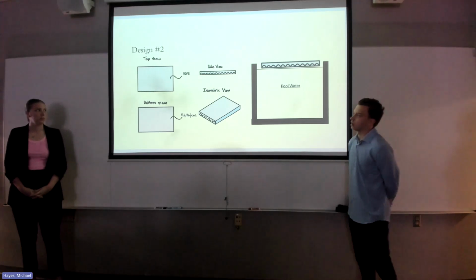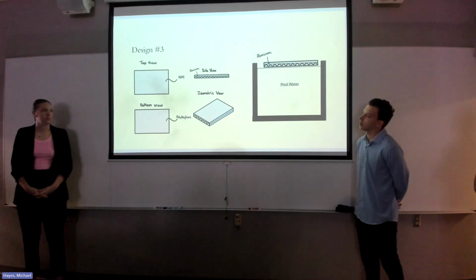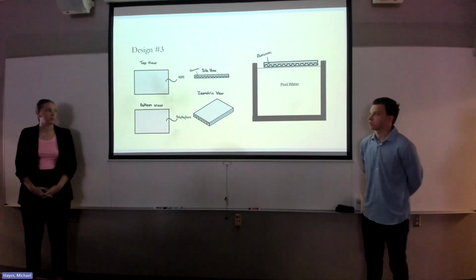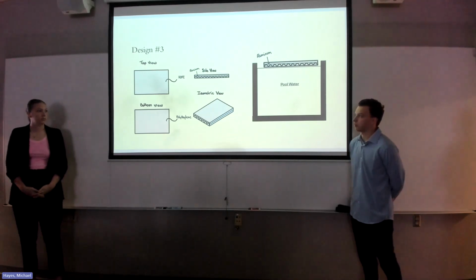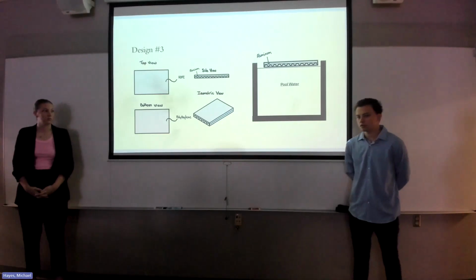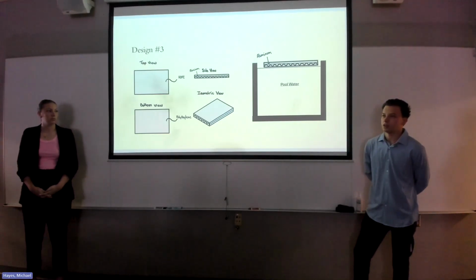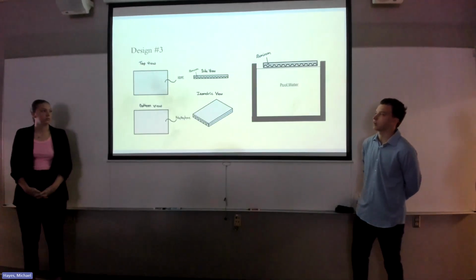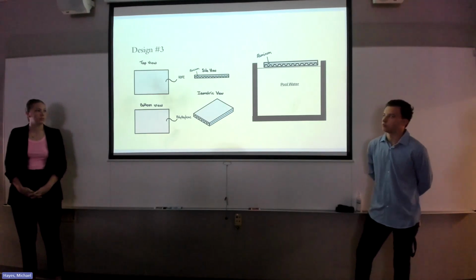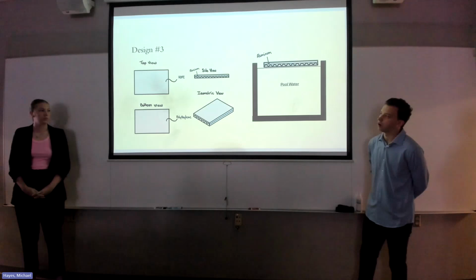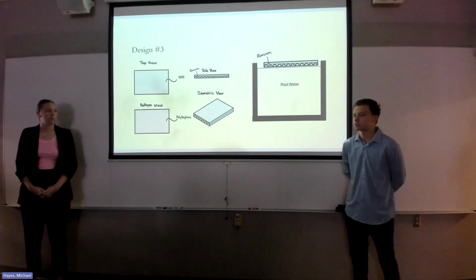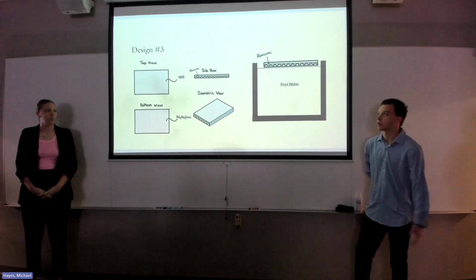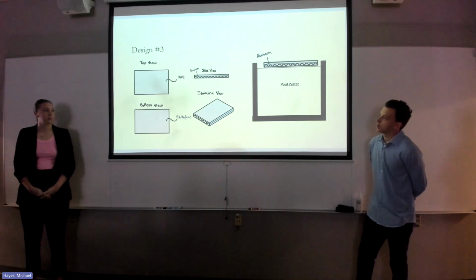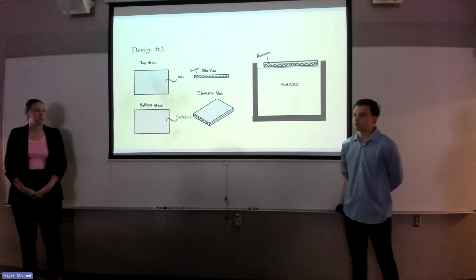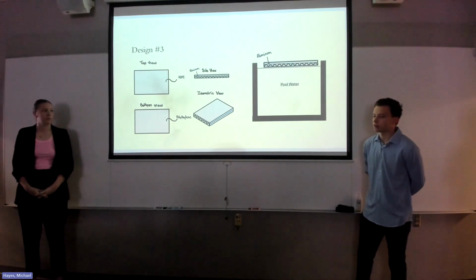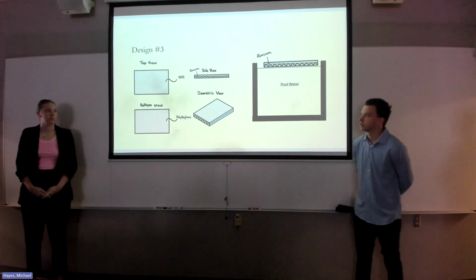And then the third design, we incorporated a thin layer of aluminum in between to increase the insulation properties so that the loss of heat at night or colder temperatures is minimized. When we were looking into research, we saw that the colors of the pool covers didn't have too much of an effect, but the one that had the most effect heating-wise was a transparent cover. But with the aesthetics, pool owners won't like a clear pool cover because it gets dirty really easily and it's really easy to see crud and stuff like that. So that's why a lot of them are blue. During the day, usually you don't have a pool cover because you're using it. So we're trying to keep as much of the water in from evaporation and heat in as possible at night and during colder temperatures. That's what we're trying to achieve here.